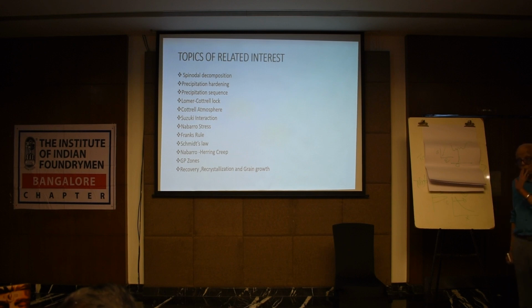That's basically the stress needed to move a dislocation. First it has to move. How does it move? You have breaking and remaking of bonds in the crystal. So that's the Peierls-Nabarro stress: how a dislocation moves. For example, in this dislocation, there are bonds. You shift the bonds, you break this bond and make the bond. That's the Peierls-Nabarro stress.